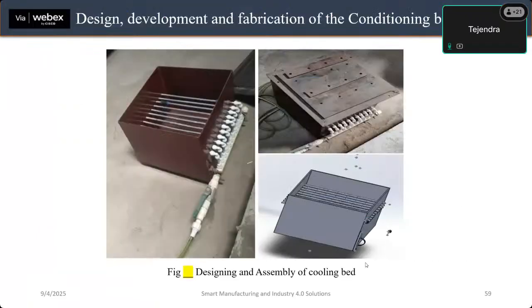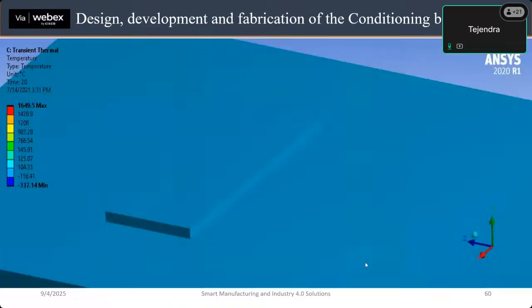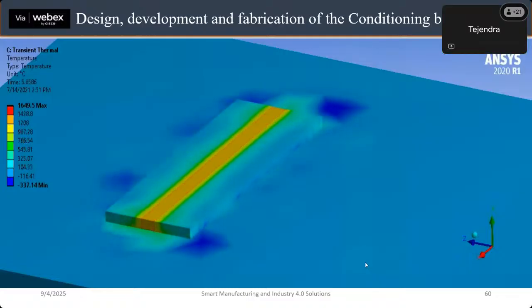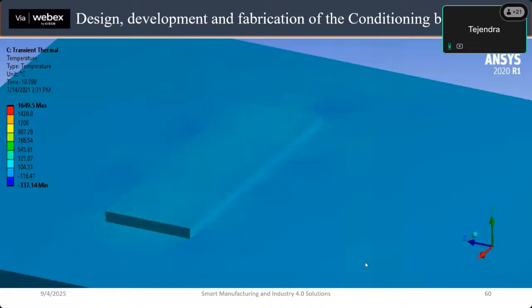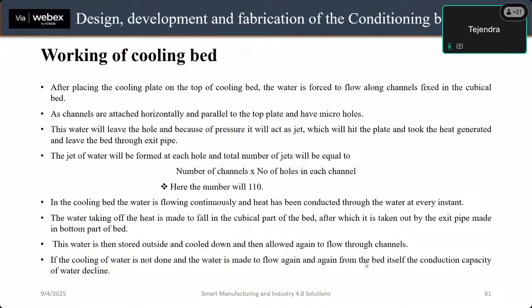Once we are done with the fluid cooled nozzle, we have prepared a cooling bed. So this is the basic design and the assembly of the cooling bed. Once we have prepared the cooling bed, we have done a transient analysis simulation on it. It takes around 17 seconds to get the temperature from 1650 degrees to 104 degrees. So that means the heat conduction through this bed is good, and because of the high heat conduction, the fluidity of material can be controlled.